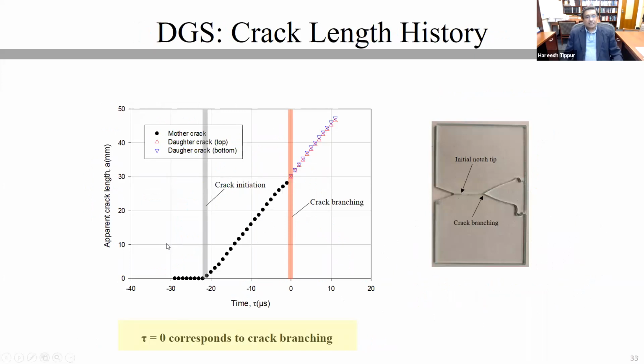The crack length history is plotted here. The mother crack is the solid symbol. The crack initiates at the gray line and branches at the red line here. Once the branching takes place, there are 2 crack tips, so there are 2 sets of symbols in the post-branching period. The sample that has fractured and been reassembled is shown on the right-hand side. Very nice symmetry. The crack propagates and nicely branches in the middle, and produces a little kink as it approaches the edge of the specimen.